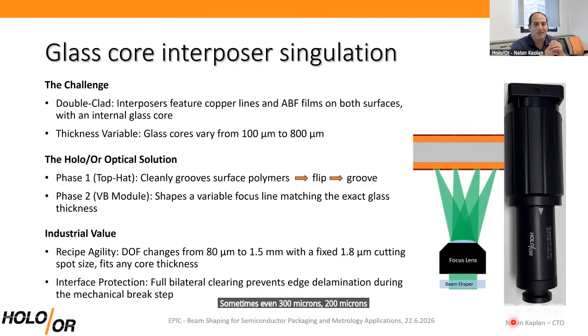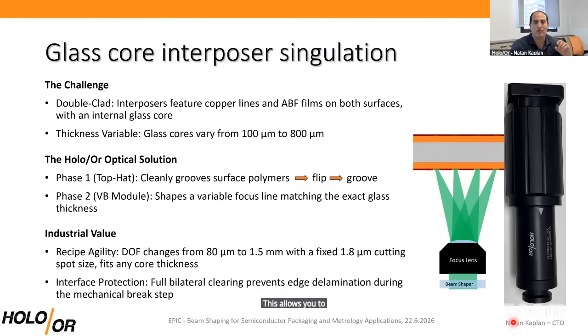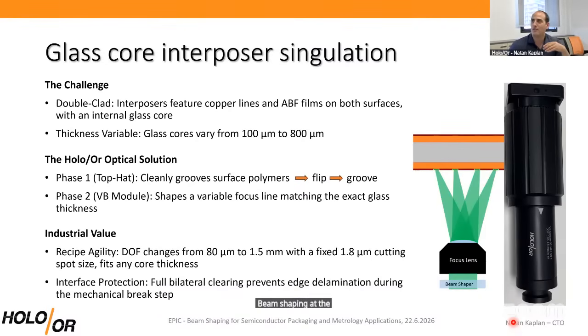The VB module is similar to the Deep Cleave, but it does not do this Z type of flat top shaping. Instead, you can play with the depth of focus while maintaining the same lobe. This allows you to adjust it for different interposer thicknesses. In this way, you can work with the same module for various lines of interposers or adjust the process exactly to the thickness of the glass you need. So again, a two-stage process, both stages using beam shaping. One, beam shaping at the plane where you create a flat top. The other one, manipulation along the depth of focus to dice the interposer.